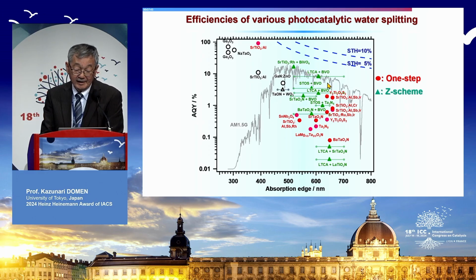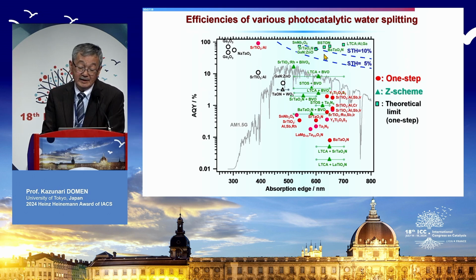But as you see here, an STH value of 5% is here or in the upper part, and an STH value of 10% is around here. As you see, we have never succeeded in getting to this region. So actually, the theoretical limit, if we use a one-step overall water splitting reaction, is around here. If we use a barium tantalum oxynitride, the theoretical limit is about 70%.